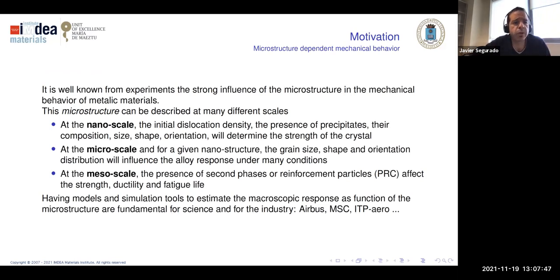But we can also refer to the microscale. So we don't see these sub-micron defects, but we see a polycrystalline microstructure. And in this case, the microstructure is the polycrystal that is forming the material. So it means the grain size, shape, and orientation distribution. And this will strongly influence the response of the alloy. And finally, at the mesoscale, we don't see the grains, but we can have larger particles, or we can have even a particle-reinforced metal, and these second-phase particles that are big enough will also affect the strength and ductility of the alloy.